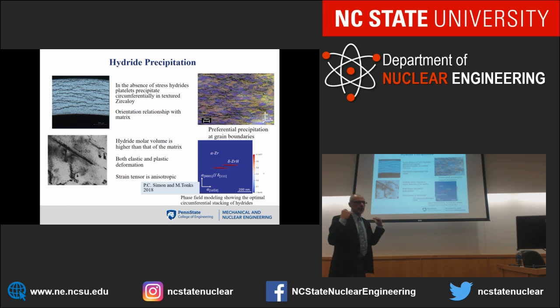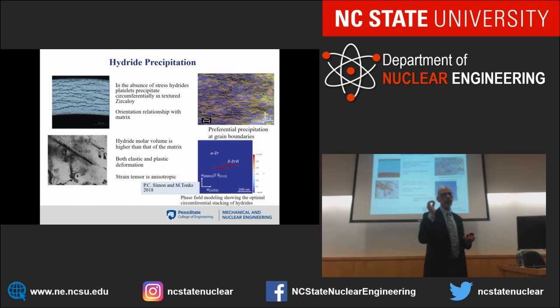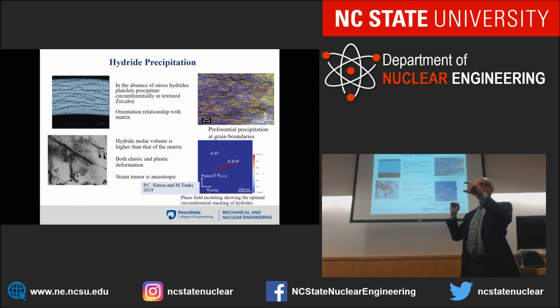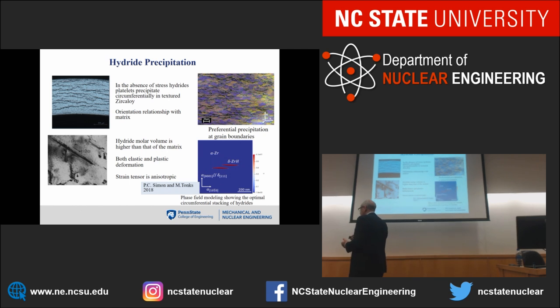After a certain level of hydrogen in the clad, I can do a thought experiment. I have a pure zirconium lattice. I introduce an atom of hydrogen, introduce another, and another, and another. At some point, this is going to become another phase. I'm going to precipitate a second phase, and that's the hydrides. The limit is expressed by the terminal solid solubility for precipitation and for dissolution, and this is what's called TSS for short.